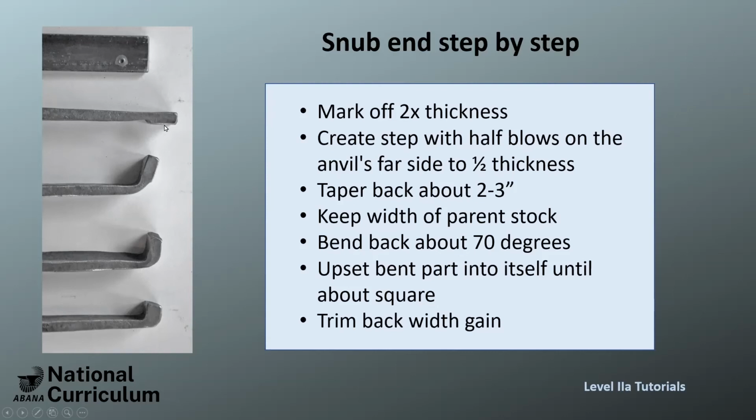If you go further than 2 times the thickness and upset, then you need to have very careful blows that you upset it in itself and don't curve it. What you see in the bottom here is I got a little curve on this picture already. This is still correctable, but if it mushrooms more here, then you have to start over again.